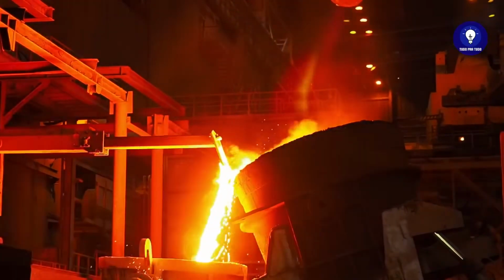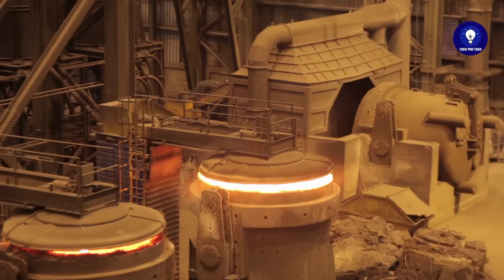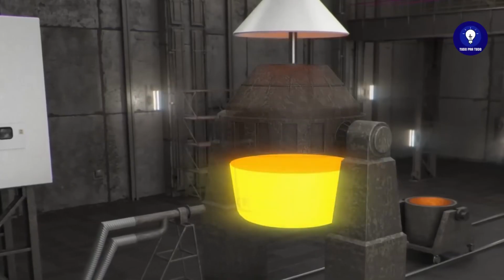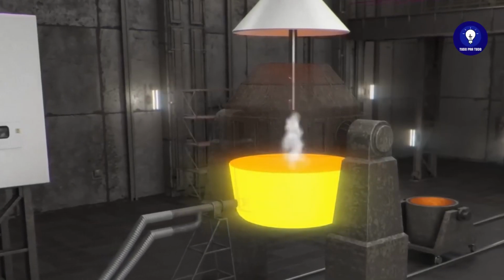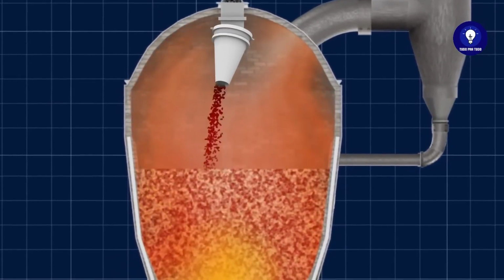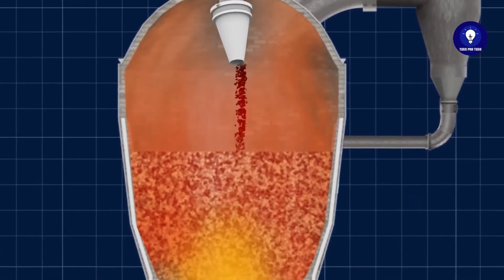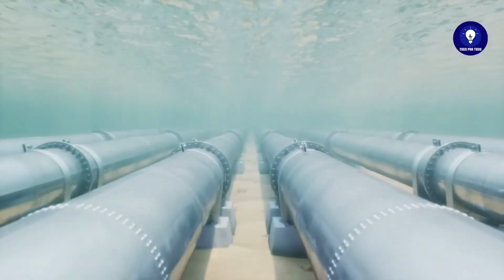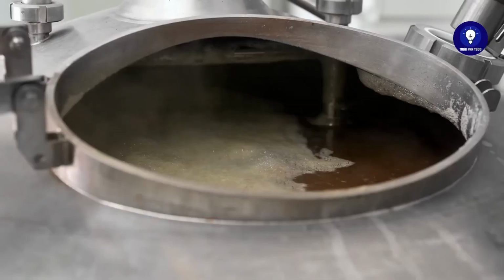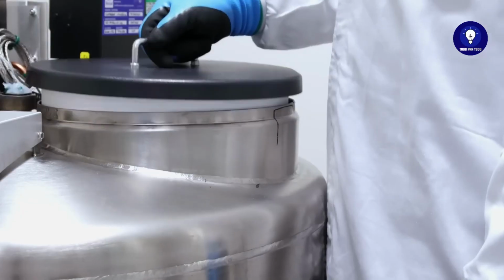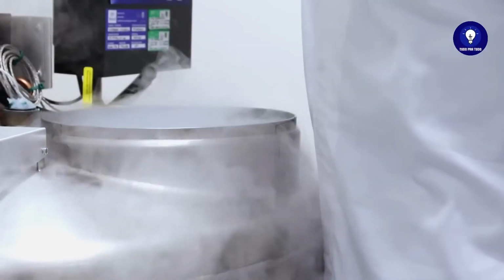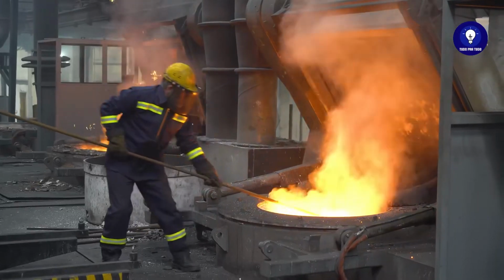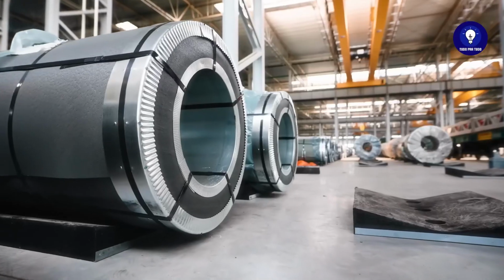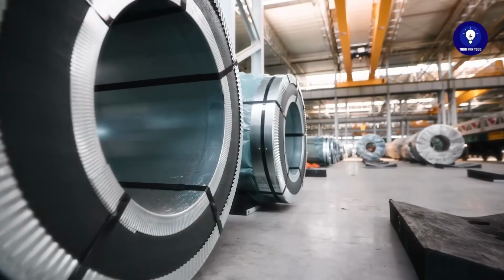Both the steel freshly produced from the basic oxygen converter and from the electric furnace go on to what's called secondary refining. There, inside covered ladle tanks, a vacuum system removes dissolved hydrogen and nitrogen, while argon jets bubble to homogenize the temperature. Calibrated additions of manganese, chromium, nickel, or niobium define specific properties. Some steels need to withstand weathering, others have to endure extreme heat or, on the contrary, be used for cryogenic tanks. The final composition follows an international standard, ensuring that the product reaches the buyer with predictable characteristics.